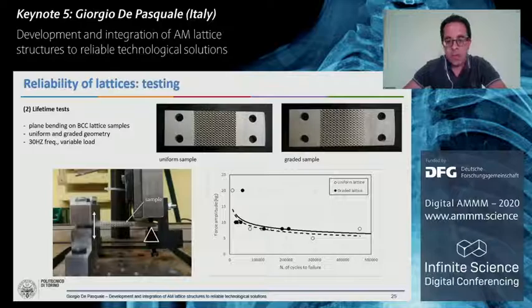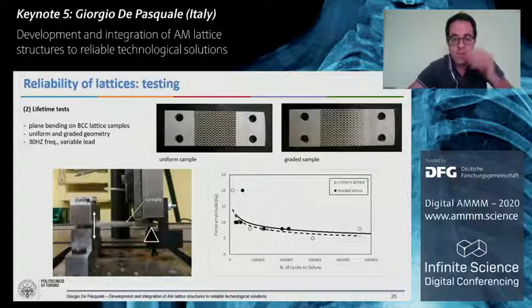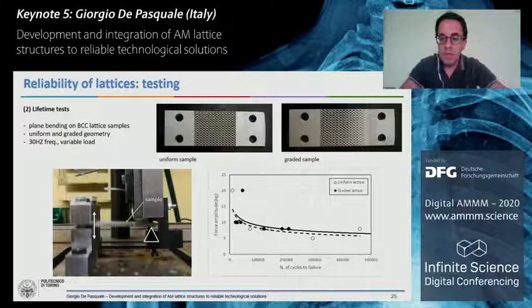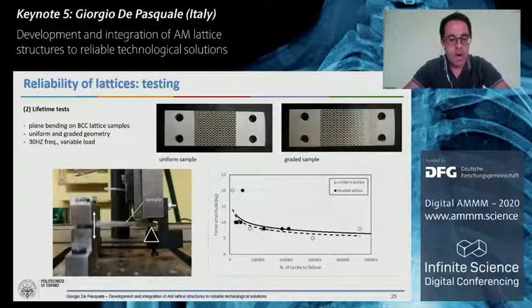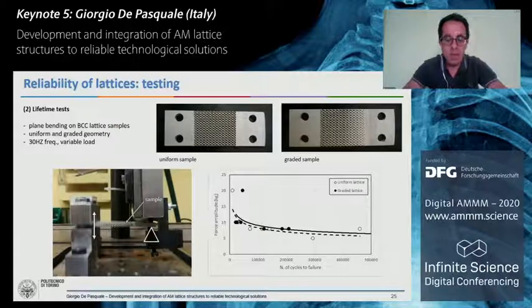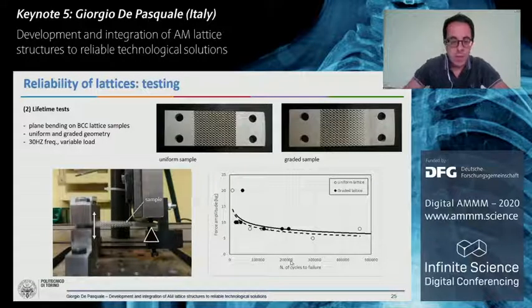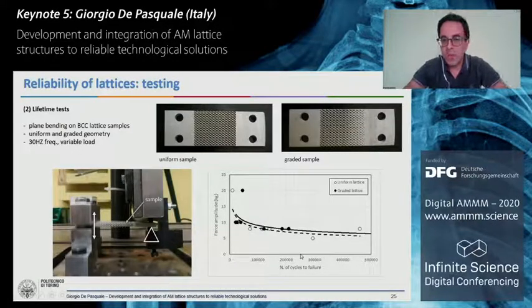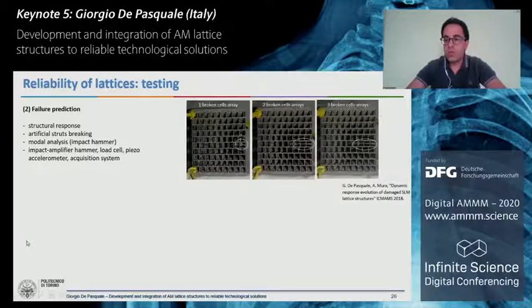From the experimental side, we have different approaches. Here I show only one, where you can see some samples in uniform shape or graded shape. In this case, we applied a cyclic load at 30 Hertz on these samples, and we simply measure the number of cycles to failure of our samples, and we try to reproduce the same behavior that we can see for traditional study of mechanical fatigue in mechanical components. The first results we have are promising because the shape of our output curves is very similar to the Wöhler diagram, and so in some ways we can use the same tools we already know.